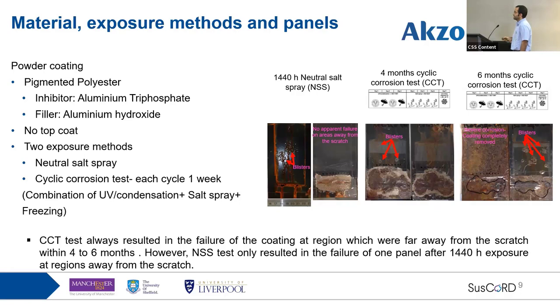We have another exposure method, which is a cyclic corrosion test, which is a combination of UV exposure, condensation, neutral salt spray, and also freezing at minus 20 degrees centigrade. As you can see on these panels that were sent to me, the neutral salt spray test only resulted in the failure of this panel, while the other panels did not show any failure. However, the panels that were exposed to the cyclic corrosion test all showed failure after 4 months, and after 6 months, some of the panels were completely ruined, and basically, I didn't have any coating there to investigate.